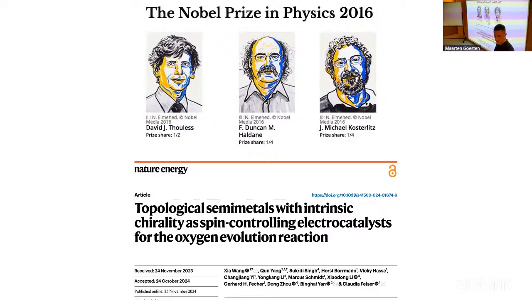And I think one of the areas in chemistry where this is really taking off is catalysis, where a lot of chemists, physicists, engineers are looking at topological materials to get better electro and photocatalysts. What they believe is that these topological surface states overcome diffusion limitations that have long hampered catalysis, and they lead to drastically improved rates of catalysis. At the same time, the theory prescribes that if you take a topological catalyst and you have a defect on the surface or you modify the surface, the topological states are preserved. There's a lot of debate about this, but it's a very interesting field to look at, the field of topological catalysis.